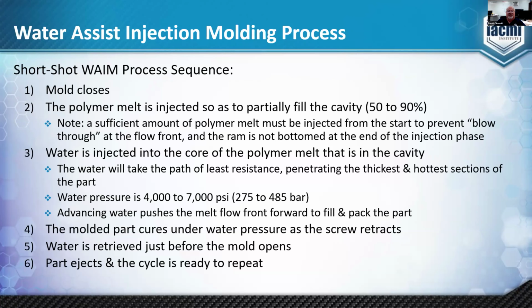The caveat, right, is that you have to inject a sufficient amount of polymer melt so that when you start to inject the water, you don't get the water to blow through at the flow front of the melt stream. And of course, at this point, the ram is not bottomed in the injection phase. The water is injected into the core of the polymer that is in the cavity. The water will take the path of least resistance, and water pressure will typically range between 4,000 to 7,000 psi. It's the advancing water front, right, that pushes the melt flow front forward to fill and pack the part.